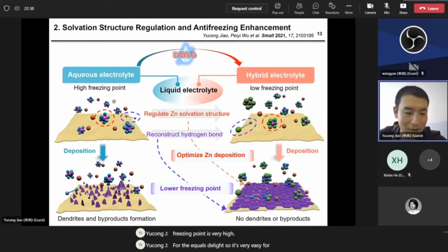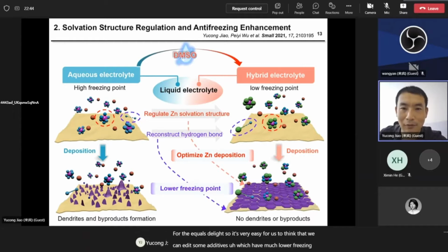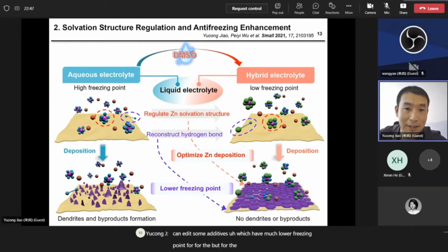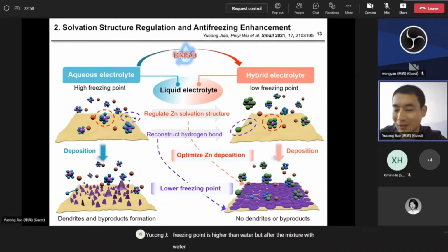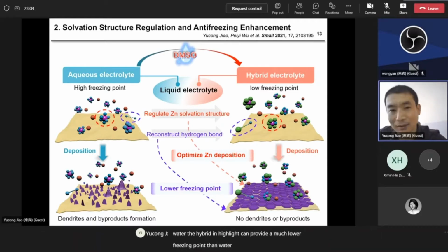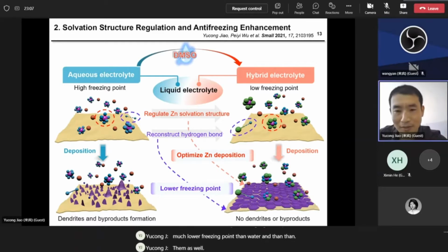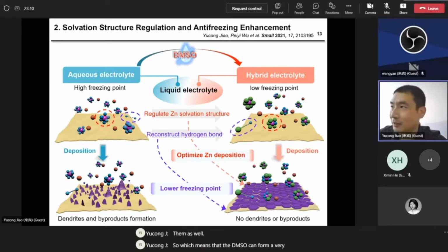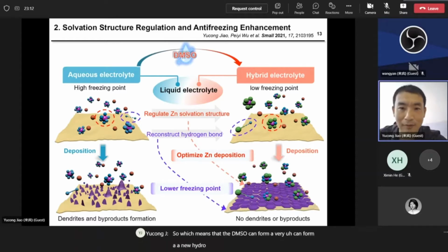So it's very easy for us to think that we can add some additives which have much lower freezing point, but for the dimethyl sulfoxide, they are more special. Their freezing point is higher than water, but after mixing with water, the hybrid electrolyte can provide a much lower freezing point than water and than dimethyl sulfoxide. Which means that the dimethyl sulfoxide can form a new hydrogen bonding with water, and this may significantly lower the freezing point.